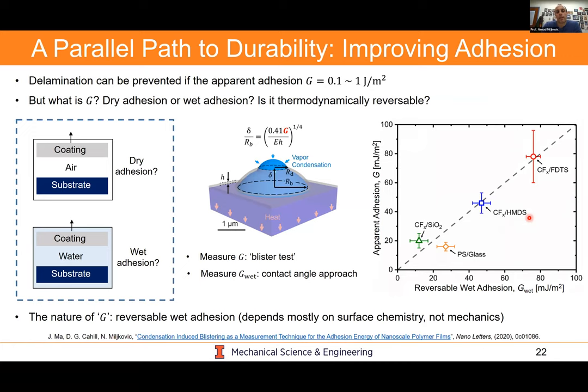What I mean by this is, a lot of scientists think that the adhesion of a coating to a substrate in air is equivalent to the adhesion of the coating to the substrate in water. If you were to ask them which one you want, good dry adhesion or good wet adhesion, they may tell you that for condensation, you want good dry adhesion. It turns out that that's completely incorrect.